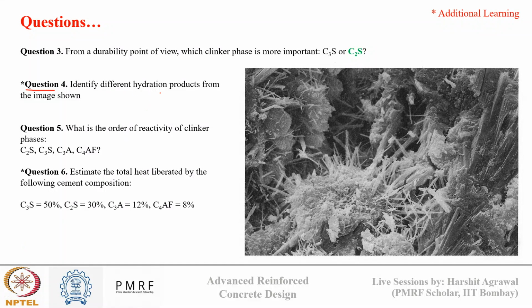Now second question, identifying the hydration products from the image. This is what I told, a 7-day hydration SEM image of a cement paste system. At the bottom left side, this is the CSH, a cement particle coated with CSH structures. These needles that you see are ettringite needles. Here at the top, this plate structure corresponds to monosulfates. And somewhere in the middle, at the right top, these large hexagonal crystals that you see are calcium hydroxide.